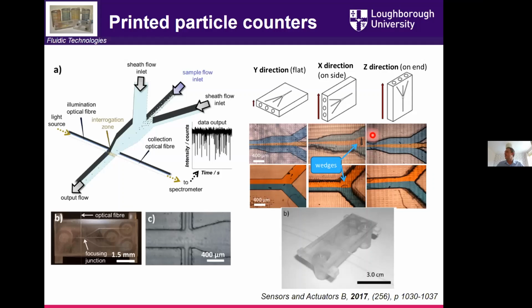And if you haven't come across doing a lot of 3D printing, let me just say that depending on how you fabricate your product in an SLA bed, it is the orientation in which you print, so you can get very different quality products at the outside. So this is the same type of device, but printed in different directions on the printer. And you get very different types of smooth features in your flow channels. Sometimes the software puts in support features just to aid the print that you're not even aware of, and it really disrupts the flow. And so you have to be careful in doing these optimizations.